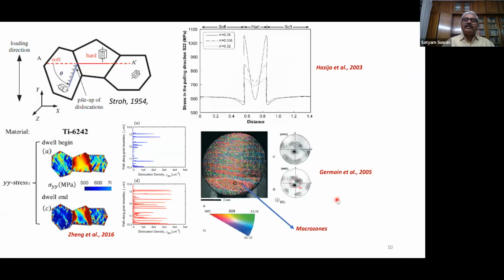So the theory behind this, the knowledge that has been generated so far, was that the first model is the Stroh model. The Stroh model says that fatigue cracks will initiate when a soft grain meets a hard grain, right? In that case, the fatigue crack initiation takes place because of the pileup of dislocations at the boundaries of the hard grain, right?